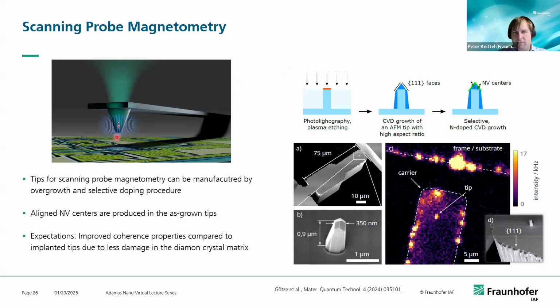And how to get these NVs into the tip? Conventionally, you implant and then produce these tips and check where you end up by a statistical approach, having a single center. So this is a process that we developed to maybe facilitate this. We've produced such tips in the same way as you've seen before for the pyramids, to produce NV centers specifically on the top facets of the tip. At the moment, these are ensembles of NV centers, so you will lose a bit of resolution, but you end up with a tip that contains the NV centers on every one of these tips. So it's not a statistical approach anymore. You can define beforehand where you get these NV centers.